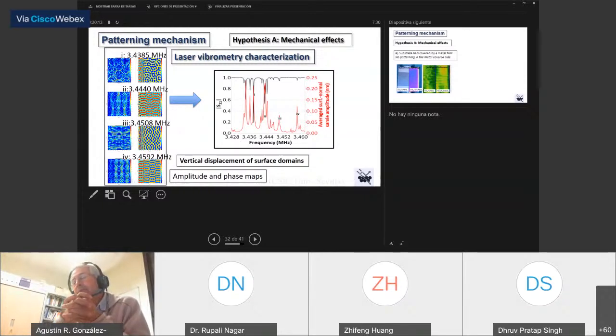Well, in principle, we have two hypotheses to deal with. The first hypothesis is a mechanical effect. So there is a certain transfer of energy or momentum of the lattice atoms, which are moving, as you have seen, for a piezoelectric substrate, and they are transferring mechanical energy, momentum to the deposited atoms.